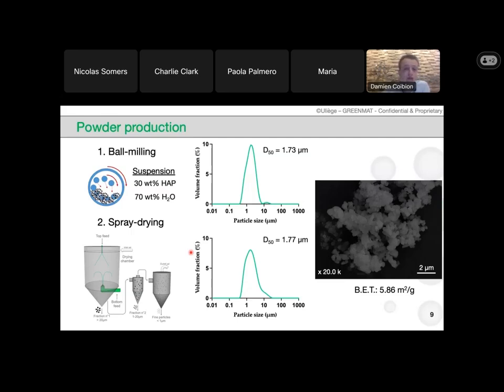And after that, the suspension is dried in a spray drying chamber. So we have a spray of micro droplets that are drying thanks to hot air that is going through the drying chamber, and we recover the powder. What is interesting here, we can see that after the drying, we still have quite the same distribution in size with almost no modifications. We still have a mean diameter of 1.7 micrometers. As you can see on the same picture, we have aggregates of these particles that are easily broken when we are preparing the paste. And we have, as I said before, a specific surface area close to 5 or 6 square meter per gram.